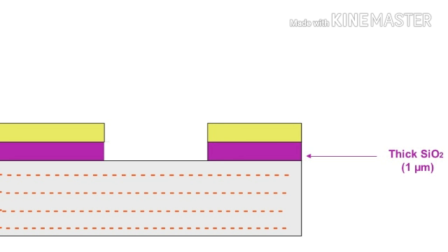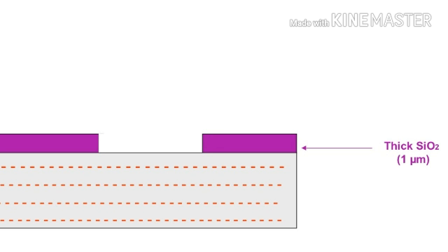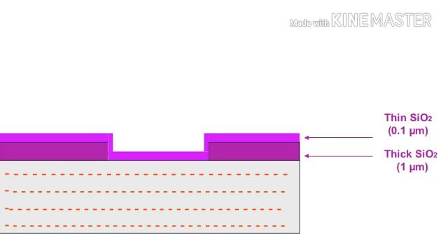By etching, we remove the SiO2 layer which is in direct contact with the etching solution. The unpolymerized photoresist is also etched away using H2SO4. A thin layer of SiO2 is grown over the entire chip area.